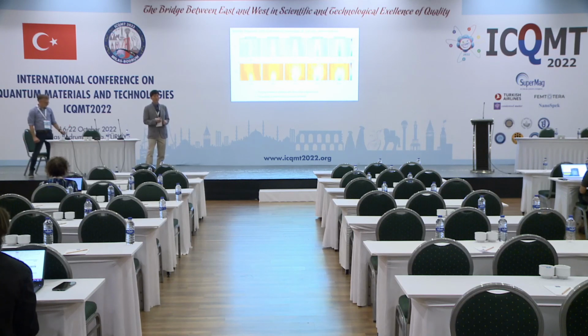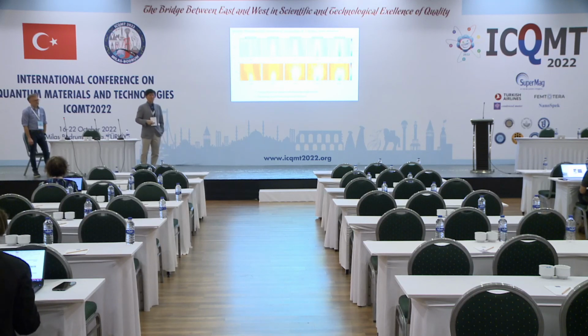I think, depending on even a tunneling measurement or STS measurement, it varies. For example, in Ali Yazdani's paper, even at around 8 Kelvin, they still see the pseudogap feature, right? So my guess is, well, I do not have any good argument, but as you pointed out, it may depend on what phase you are looking at, and also the conditions of your contact. In my case, those may play a role. That's my guess. And also, if you look at this part, it's kind of very blurry, right? And at which point you put the T sub z, so at this moment, I don't think I can give you a very good answer.